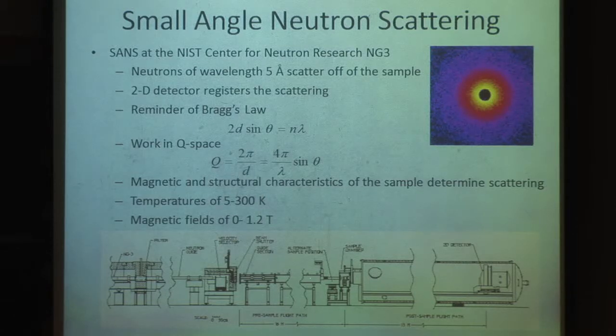We work in Q space instead, where the relations are as shown. So the magnetic and the structural characteristics of our sample determine how things scatter. So it's sensitive to both the actual crystal structure and to the magnetic effects of our sample. So we worked at temperatures from 5 to 300 Kelvin and fields from 0 to 1.2 Tesla.